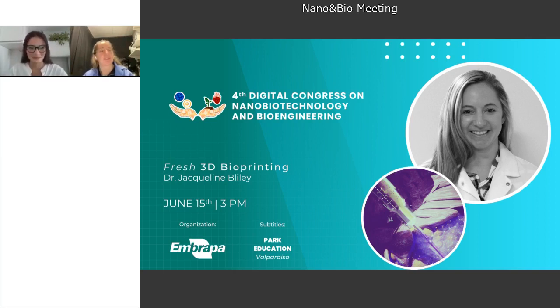So thanks for the question. It really depends on the size of what you're trying to print and the resolution that you would like to print. For us, you can see a lot of our prints are very high resolution, and we're trying to capture the very small features. So something like a full adult human heart, that alginate print that I showed you, took like 2 days to print. However, there is some leeway with how much resolution you need for printing. We probably don't need to print all the very tiny parts of structures, and we can probably get away with lower printing resolution in certain areas.